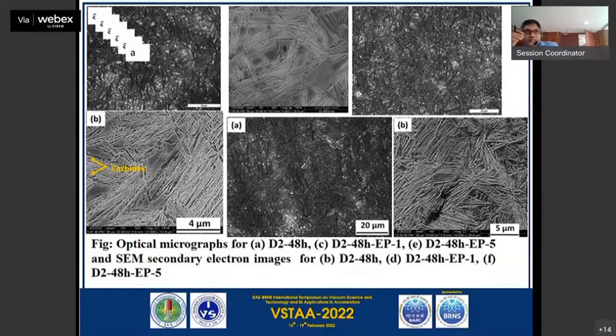But there is some decomposition of this austenite as well as bainite, and a very minor amount of fine carbide particles is there. And when we continued this pulsing, we saw that the amount of bainite almost remains the same, and the microstructure is stabilized. However, some part of the fine carbide that had formed got dissolved. Next slide, please.